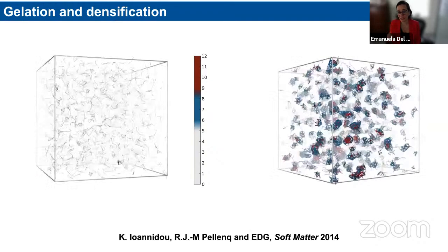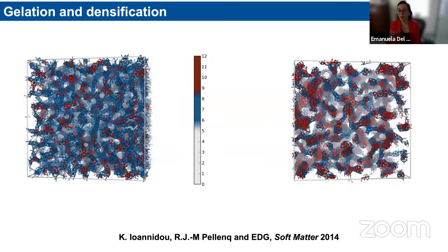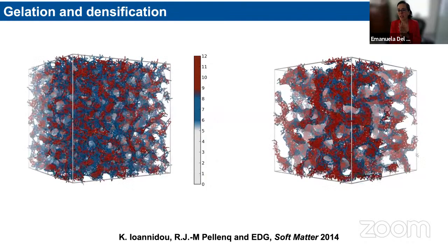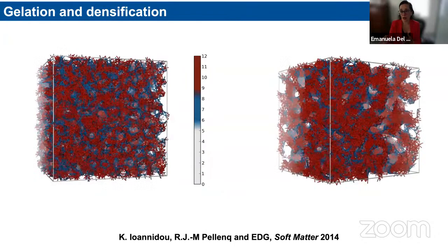So you see basically that as precipitation and aggregation goes on, you get more or less the same type of process, but now the structure that you form in the beginning, because the shape of the interaction is different, they are actually much bulkier. You have bigger clusters, a wider distribution of pore sizes, and the gel densifies over larger regions.